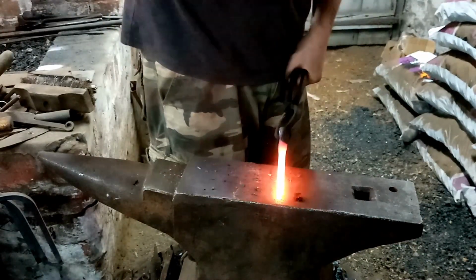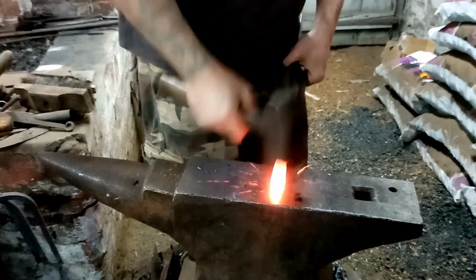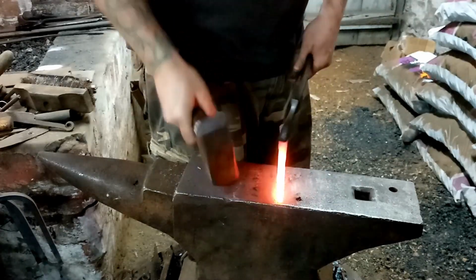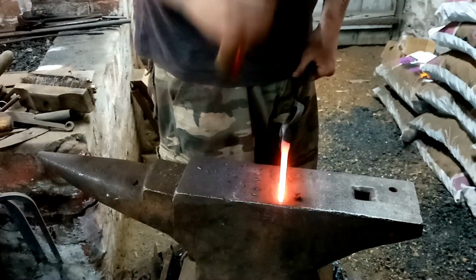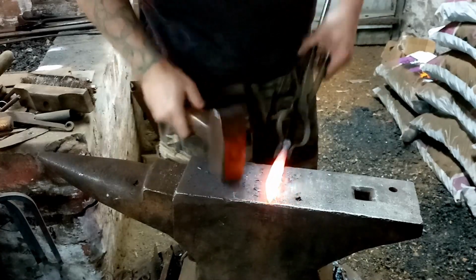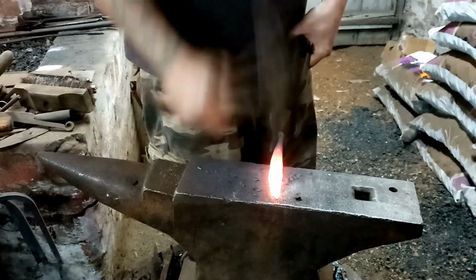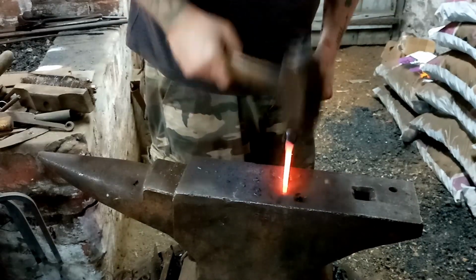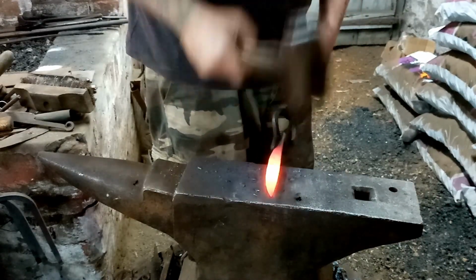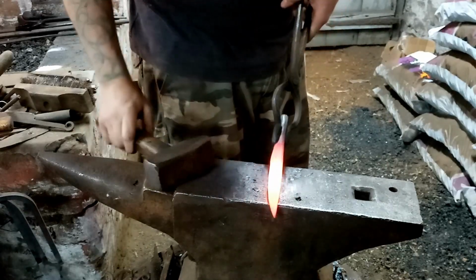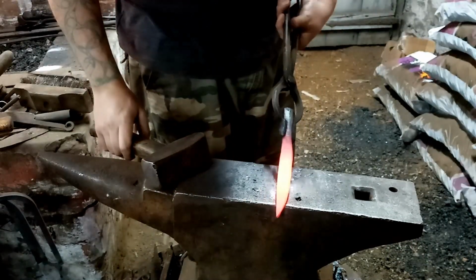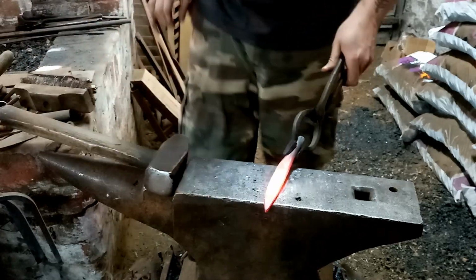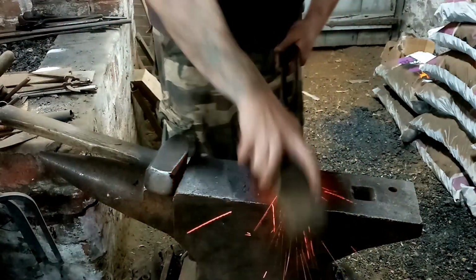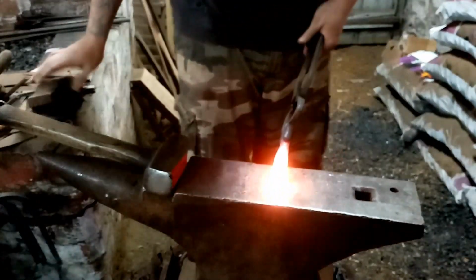But as you forge that point down, make sure you turn the metal flat onto the anvil and stop it from galling, giving it a few hammer blows near that tip to make sure the metal isn't folding in on itself and creating a gall. Basically a flaw in the metal, which later on could cause it to snap, could cause problems when heat treating, or if it somehow makes its way all the way through the process without you noticing, it could cause that tip to snap off when it's first used. So make sure you keep that nice and level as you go.